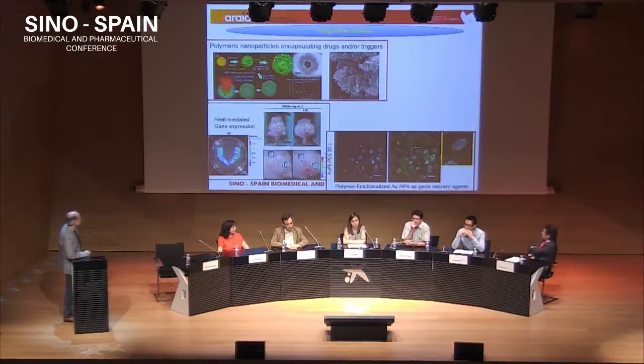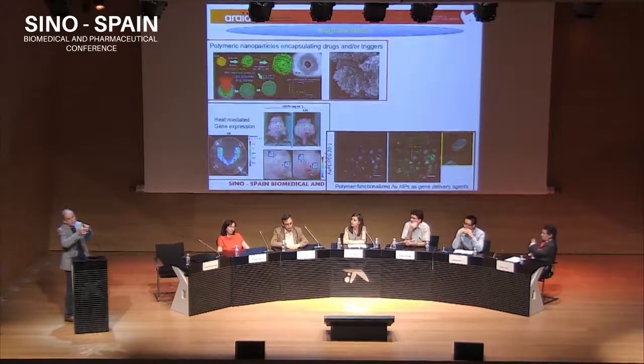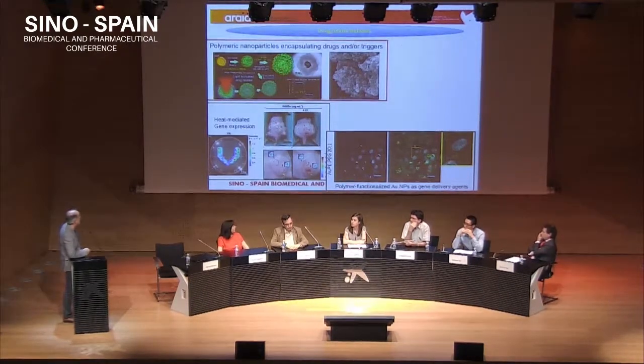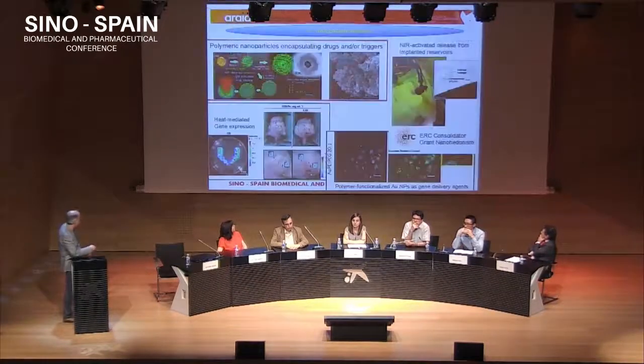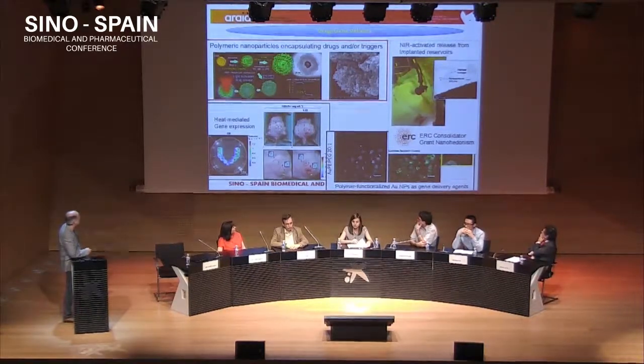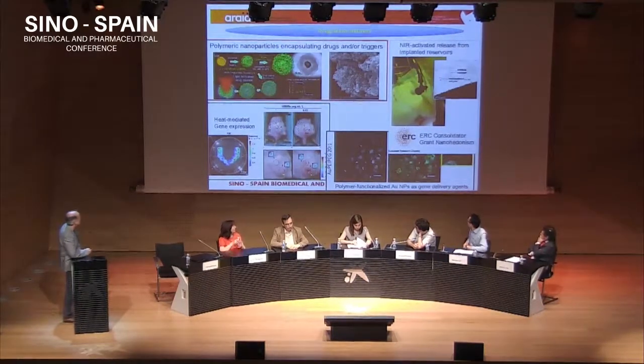Here, this is a very interesting example. We do this in collaboration with the Hospital La Paz in Madrid. This is heat-mediated gene expression. So what our collaborators do there, they make a construct mediated by a heat shock protein, and the heat shock protein controls the expression of a gene. In this case, you can see this is a culture plate, so we put the laser, the nanoparticles together with the cells that express this gene, and we can control the expression of the luminescent gene by controlling the region of laser irradiation.